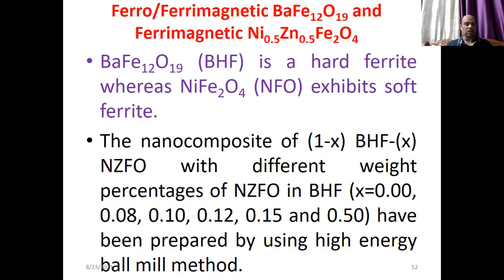So what you have to do is prepare the materials separately, do the ball milling to bring them together, then sinter it and make a nanocomposite pellet. Suddenly it will come to mind that if I heat it at a high temperature, they will again become bigger in size. When you heat a material at a higher temperature, it becomes bigger in size, if another material is available sidewise, they diffuse. But in the composite, interestingly, it will not increase its size, except that it makes a harder material, because different grains are together.